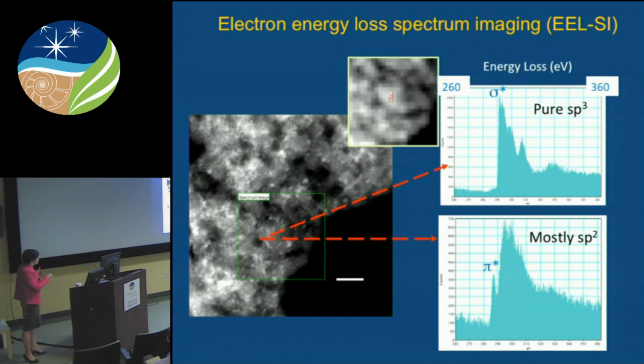We can not just measure the crystal structure, but we can confirm where we have diamond and where we have disordered carbon. We can look at the bond structure of the sheet carbon and distinguish based on the electron energy loss spectra. So this is the carbon K-edge spectra. We can see where we've got pure diamond. So this is the fingerprint signature of sp3 carbon at the interior of this 2 nanometer diamond. The scale bar is 2 nanometers.